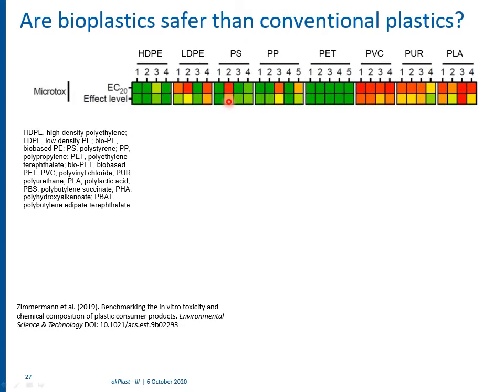And as has been expected, the highest toxicity was observed in the extracts of the polyvinyl chloride and polyurethane-based products. And what has been actually unexpected is that very high toxicity was also observed leaching from PLA-based products, so from the bioplastics. However, you would perhaps consider this to be less surprising if you remember that biodegradable plastics need or might need a higher level of biocides and stabilizers to remain functional during the use phase.